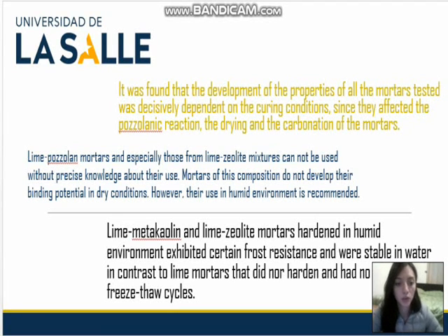Another conclusion is that lime-pozzolan mortars, and especially those from the lime-zeolite mixtures, cannot be used without precise knowledge about their use. Mortars of this composition do not develop their binding potentials under dry conditions. However, their use in humid environments is recommended.